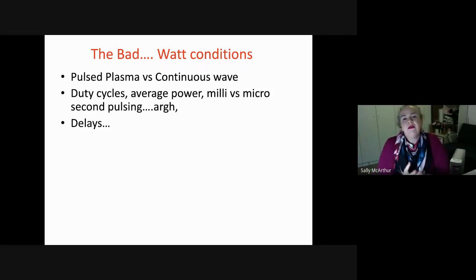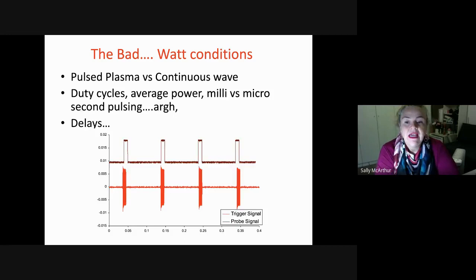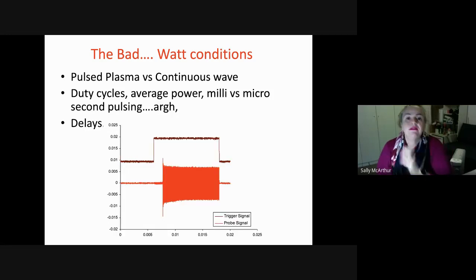But there are also issues with the types of pulsing that you do and the ability to monitor that pulsing. A lot of people pulse systems, but they're not actually looking at the way the energy is delivered in the chamber. That's an interesting question, and one that we've looked at in the past. When you're doing a pulsing regime, what we found is you can have delays in your system. You have your trigger signal, and then you can probe using an electrode probe inside the chamber to look at what is actually happening. When you look closely, you can see that there is a delay in the actual signal going through.